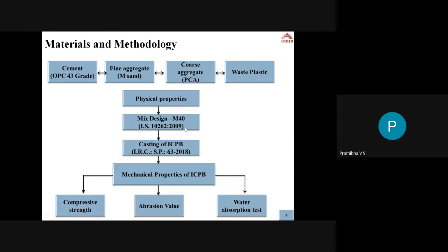Then the mix design: M40 grade of concrete is used for the interlocking paving block preparation. As per IRC 63, if we are using interlocking paving blocks in a residential track, the preferred grade of concrete is M40, so we have used M40 grade concrete. The casting is also done as per IRC SP 63, where the preferred minimum thickness for the paving blocks is 6 centimeters, or 6 to 8 centimeters. After casting, the ICBP is tested for mechanical properties at different curing durations: 7, 14 and 28 days. Compressive strength, abrasion value, and water absorption tests are conducted.